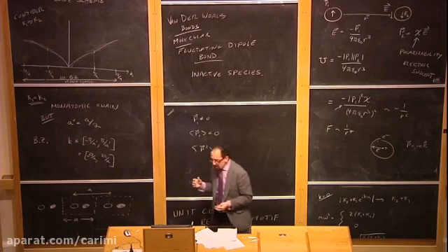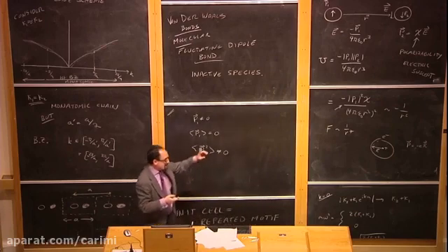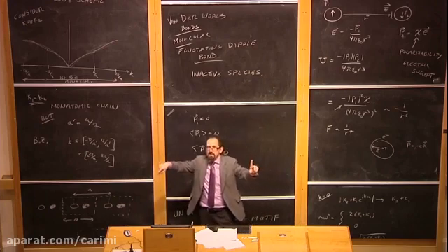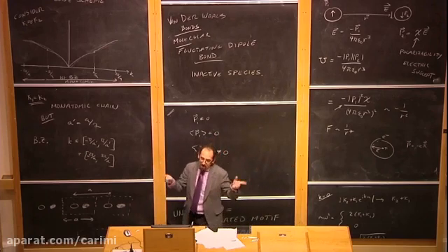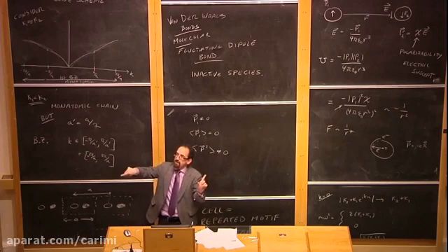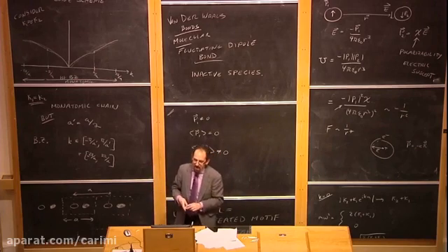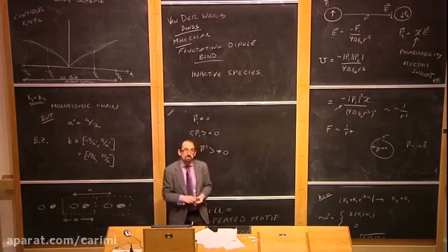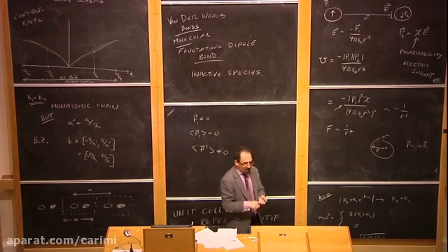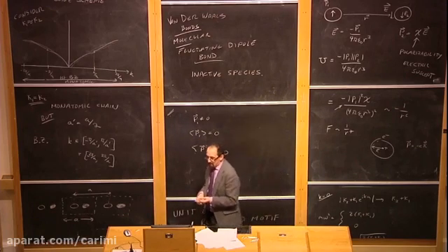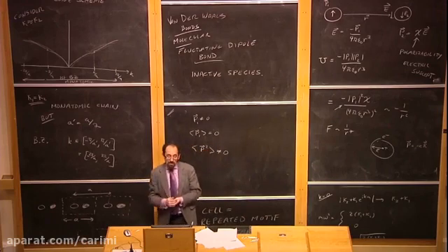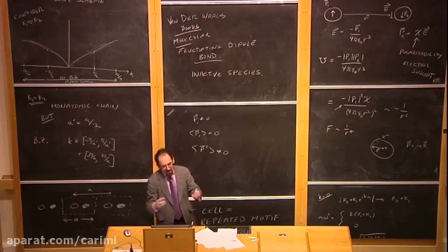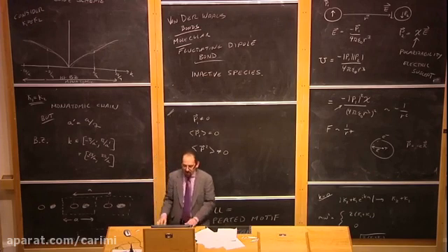Anyway, so you get a little bit of a fluctuation on one atom. It causes a fluctuation in the other atom, and they attract. And no matter which direction the fluctuation is, the responding fluctuation is in the opposite direction, and they always attract. So you can still get a non-zero van der Waals force. Now, the van der Waals force is much weaker than covalent, ionic, or hydrogen bonds, but it's still strong enough to cause important effects, such as holding together argon at low temperature when argon becomes a solid.